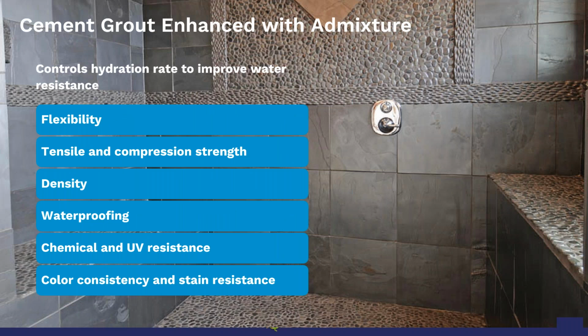So cement grout can actually be enhanced with what we call an admixture. An admixture adds additional properties to the cement grout to give you a more consistent cure result as well as improve the performance. There are different types of additives, but the one you're going to use most is latex additive, and that allows it to bond tightly around the sand and the cement particles that are in the powder mixture itself, creating a more cohesive mass and linking of the bonding, reducing the water absorption rate and making it stronger and more stain resistant.